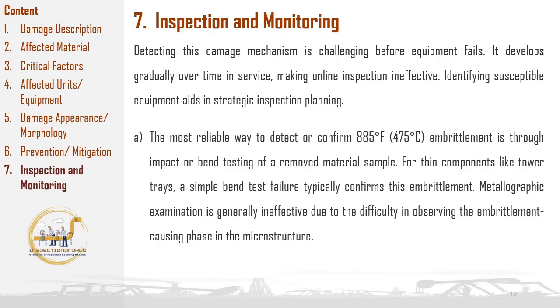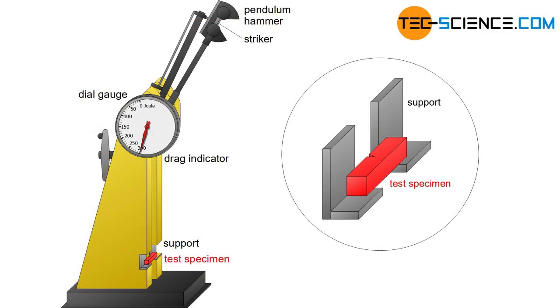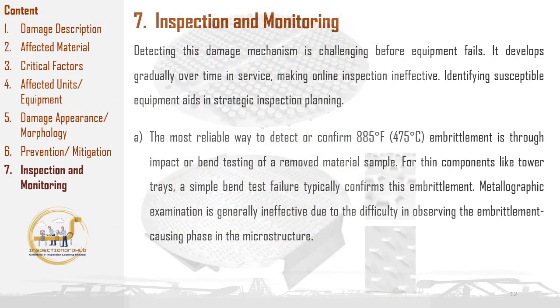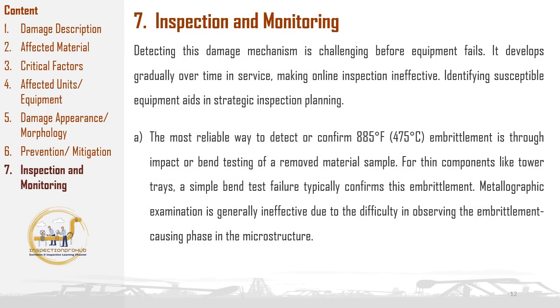The most effective and reliable method for detecting or confirming this type of embrittlement involves removing a sample of the suspect material and subjecting it to impact or bend testing. This approach is particularly useful for thin components such as tower trays, where a simple bend test failure can provide strong evidence of embrittlement. It's important to note that metallographic examination is generally not effective in identifying this damage mechanism, as the embrittlement-causing phase is often difficult to observe in the microstructure.